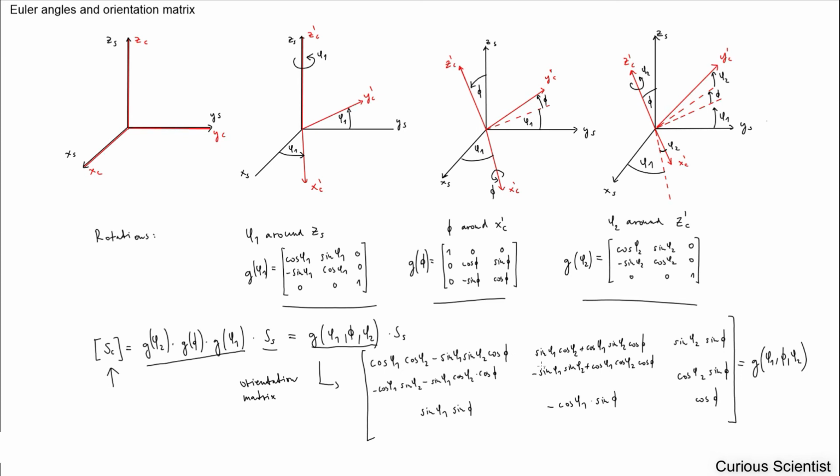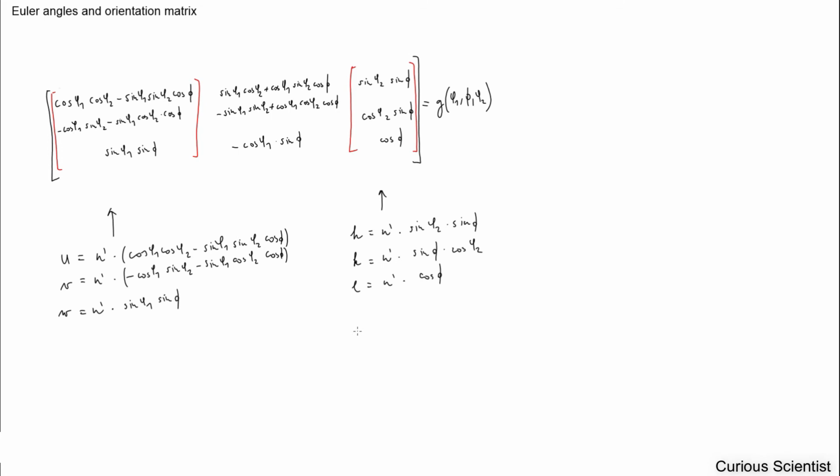Now what we can do, I can show you a very simple way to use this orientation matrix or rotation matrix. This is just one example, but I will show you several more later on. I moved the matrix from the previous picture here. One nice property of this matrix is that if we take the first column and the last column of the matrix, we can get the HKL coordinates and the UVW.